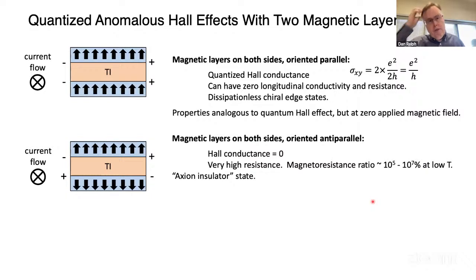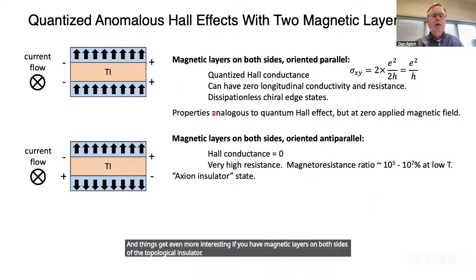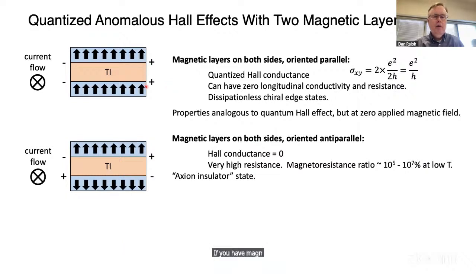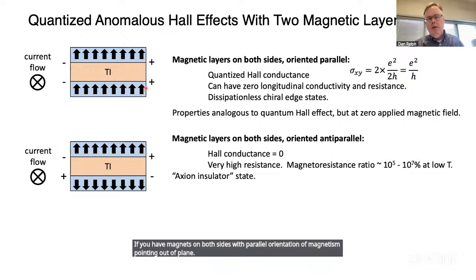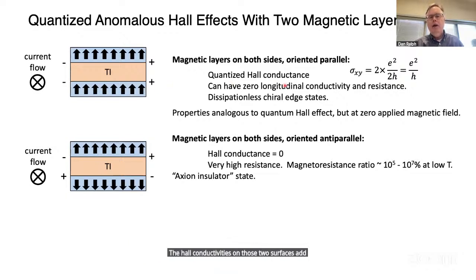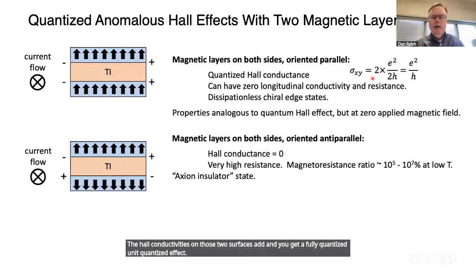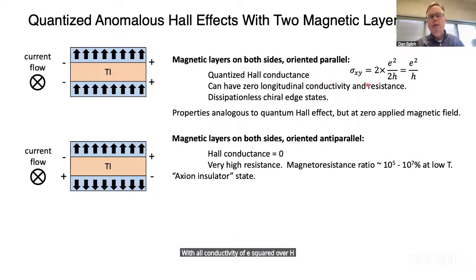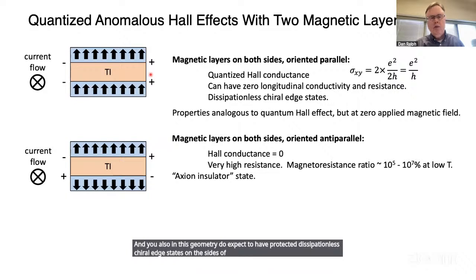Things get even more interesting if you have magnetic layers on both sides of the topological insulator. If you have magnets on both sides with parallel orientation of magnetism pointing out of plane, the Hall conductivities on those two surfaces add, and you get a fully quantized, unit quantized Hall effect with a Hall conductivity of e²/h rather than e²/2h. And you also in this geometry do expect to have protected dissipationless chiral edge states on the sides of the topological insulator as well.